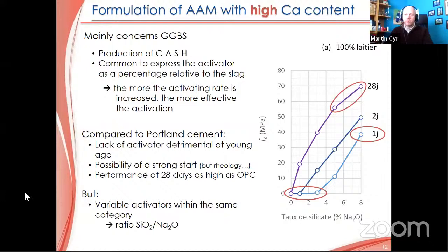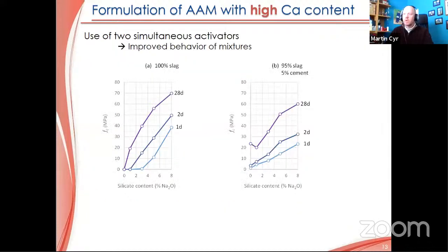But of course, we can have variable activators within the same category, meaning that the ratio of silicon over alkali will change a lot and will influence a lot the final properties. We can also use two activators at the same time. For instance, here using a little bit of cement as an activator also, in combination with sodium silicate. It's funny to see that cement itself is not now the main material to make the concrete, it is the material used as a chemical. And it's funny to see that sometimes.